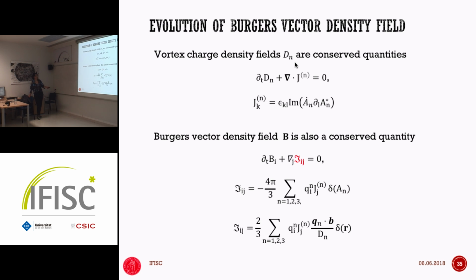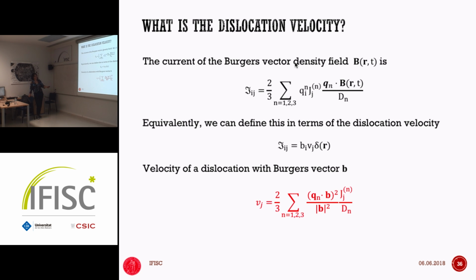If we use this definition before, well, there's a couple of steps, but basically it can also be written like this. Now, if I substitute the zeros of the order parameter through the Mazenko transformation, I can relate it to the location of the dislocations and the Jacobian of the transformation. So then we have this expression for the current associated to the Burgers vector. But this current can also be written as an advection current. So if I have a dislocation at position r0 that is moving with a certain velocity v, and it has a Burgers vector b, then I can construct, by definition, the current that it carries. So by just identifying these two expressions, we can predict the velocity of the dislocation directly from the evolution of the phase field.